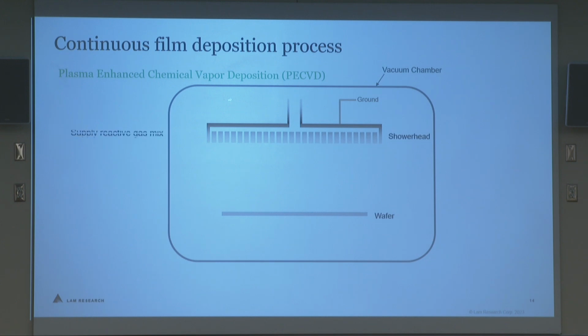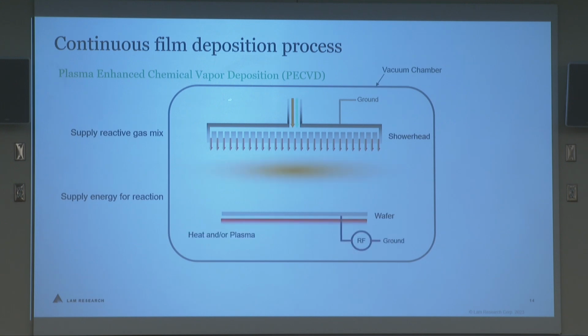You've got a wafer, and you supply a reactive gas mix into the chamber, and you supply energy for the reaction, and that is often either temperature or a plasma in the chamber. And that creates the energy that the chemical reaction needs to take place. So you get your reaction and you build up your film. And that's done continuously where everything is at the same time. As an example, silane plus ammonia is going to give you a silicon nitride film.